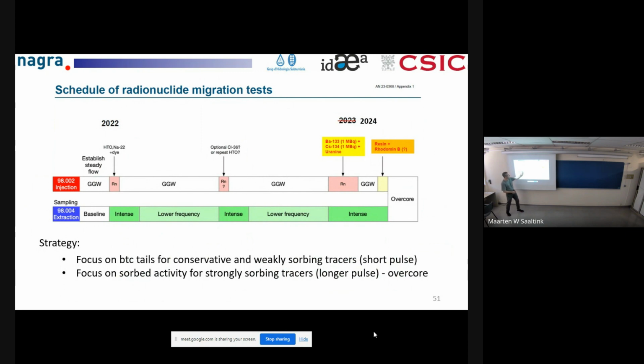We've already done this part. First we inject water, and you make sure you have a steady state flow regime. Then we do the 20-hour pulse, which was tritium, sodium-22, and uranine. The point with the uranine is that you can measure in situ. The tritium and the sodium-22, you have to take samples and take to the lab. So 20 hours, and then inject for a long time just Grimsel water and look at the tails.